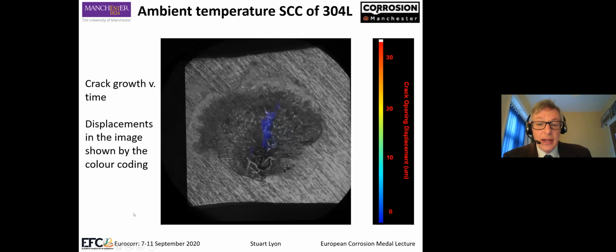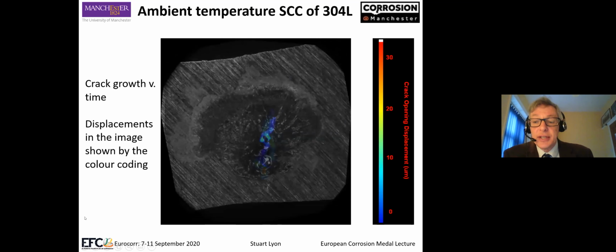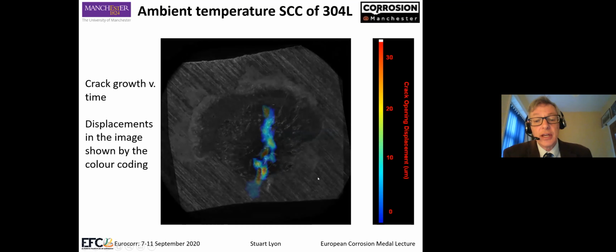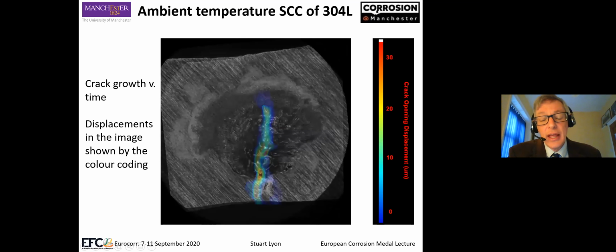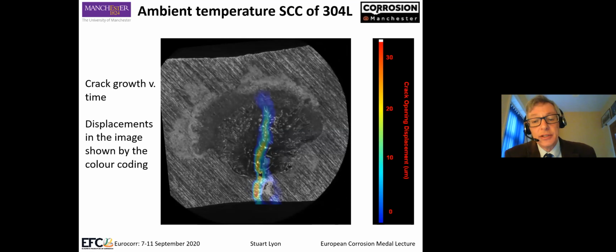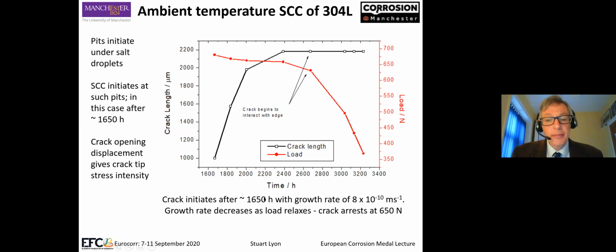You can see the crack. As the crack develops, this color-coded scale shows the lateral movement in the sample by digital image correlation, and we can see the crack is actually bifurcated at that point there. There are 2 cracks here. There's a pit, a crack has grown that way, but it's mainly grown that way. So the pits initiate under salt droplets, and stress corrosion cracking initiates in this pit after some kind of initiation time, a delay time, in this case around 1650 hours, that's about 10 weeks.